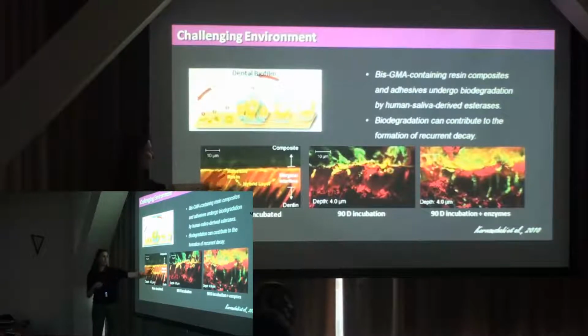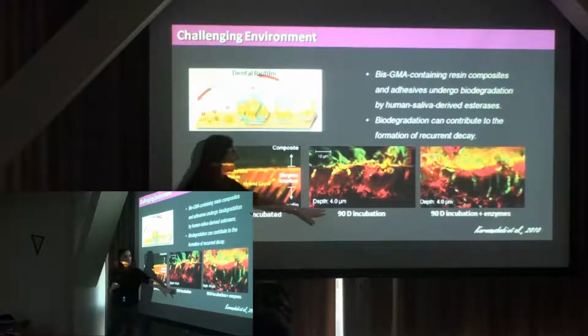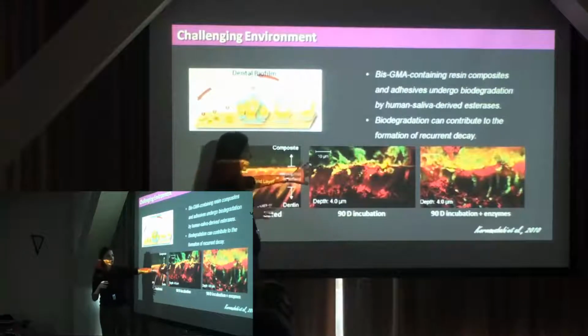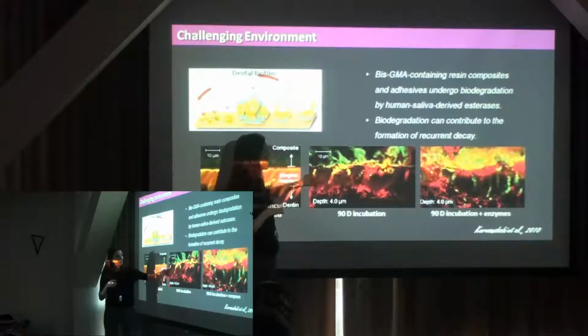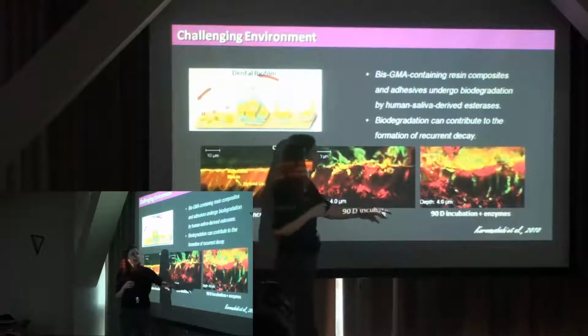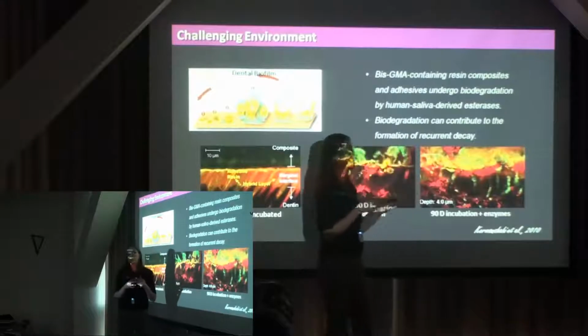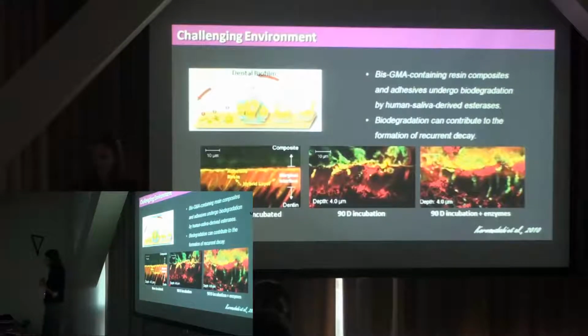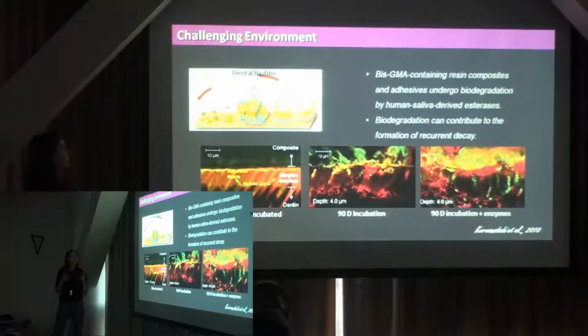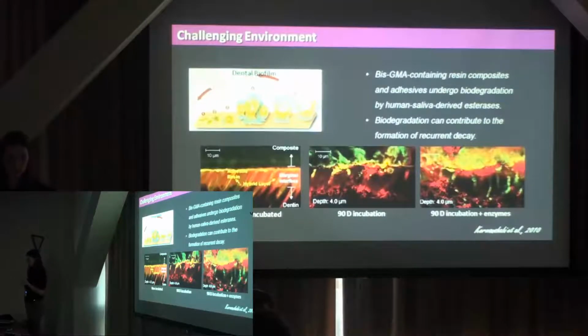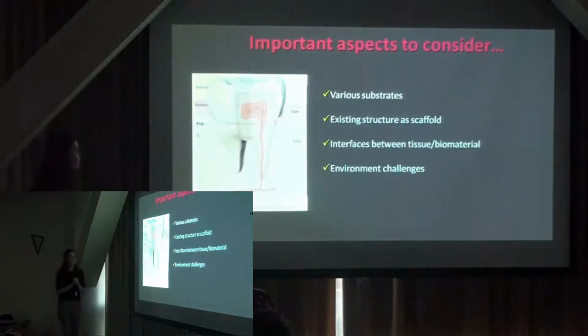But what they did is that this is when you just restore the tooth surface, so everything looks very nice and neat. 90 days later, when they incubated these in water, you start seeing some disruption, and you can find bugs into this interface. And when you introduce enzymes, you have really a much more drastic breakage of that interface. So now we know that we have to deal with this issue, and that's why now the National Institute of Health has proposed a new RFA to try to fix this problem with the current system. So maybe we have composites that don't create this ideal environment for the bugs. All right.